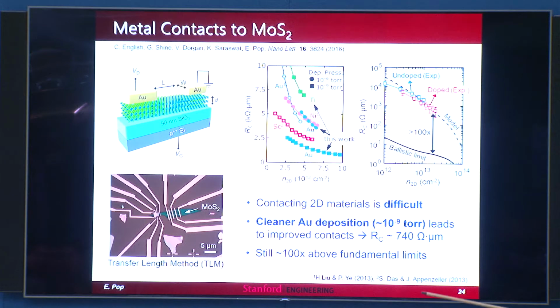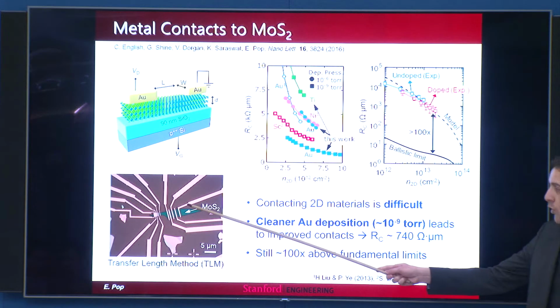And lo and behold, maybe in retrospect this sounds very trivial, but we realized that if you deposit gold in the cleanest evaporator that you have, the one with the load lock, the one with the really low base pressure, you can get much better contacts than if you do it in a more dirty, run-of-the-mill evaporator. Titanium contacts are particularly bad in our experience. We avoid titanium at all costs because it either attacks the sulfur, so it makes titanium sulfide, or it just oxidizes. In fact, in the poor evaporators, titanium basically gets down and becomes titanium oxide. We've seen this by XPS, and other groups have seen it as well. So as much as possible, we use pure gold for our contacts.